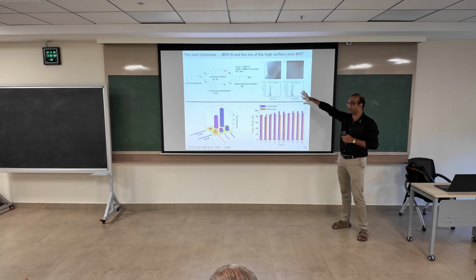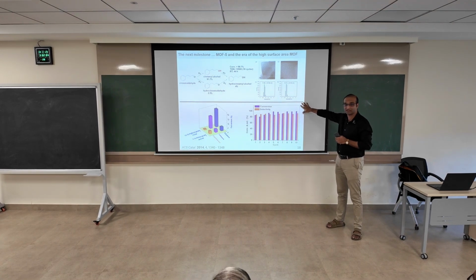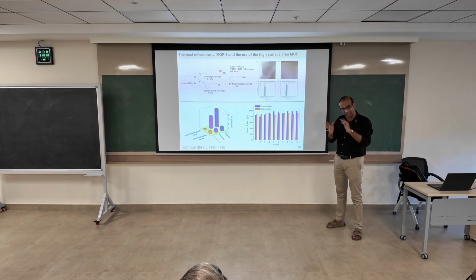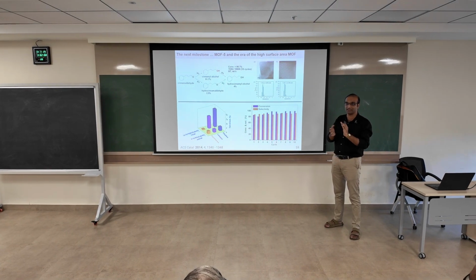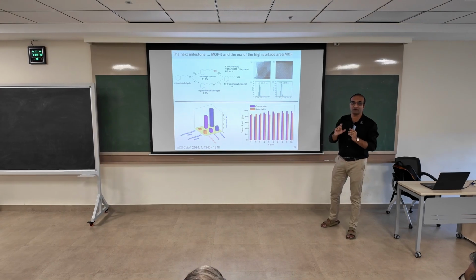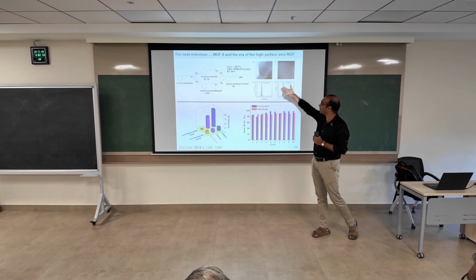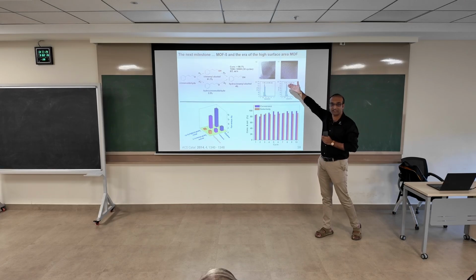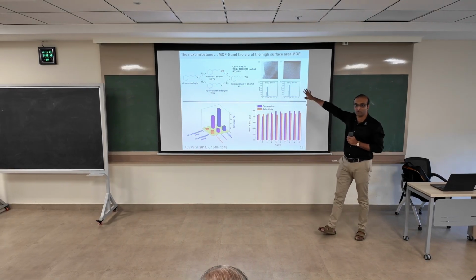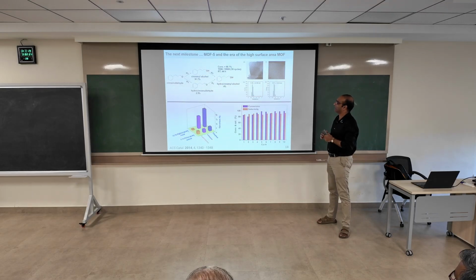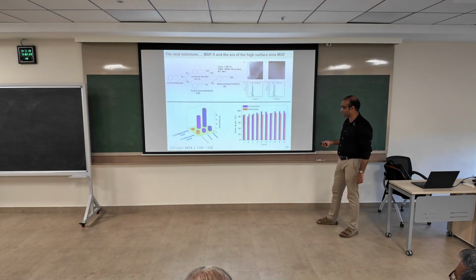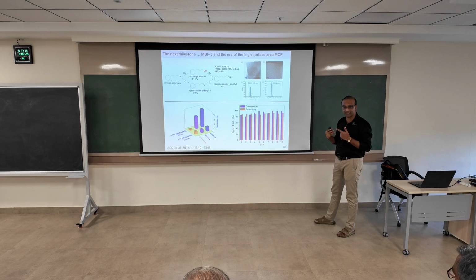Of course, when the reviewers saw this image, they didn't believe us. They asked us to do TEM by rotating the sample and seeing all across the angles. You have to show a 3-dimensional video of how the thing actually is inside, because when you look at this 2-dimensional image, you cannot tell. It could be outside the platinum nanoparticle, right? But we did all that and we proved to them that it is inside. And then we showed that it could be stable for almost 10 cycles. You can recycle the catalyst 10 times, keep on reusing it, okay?